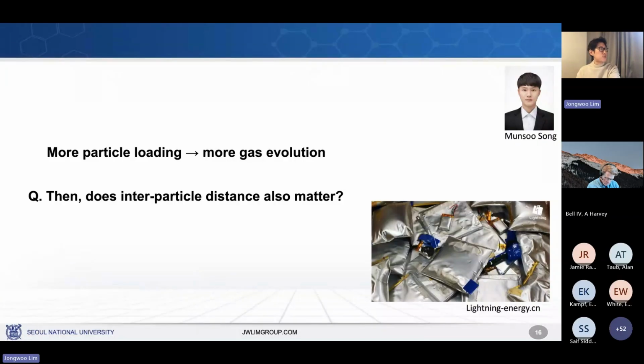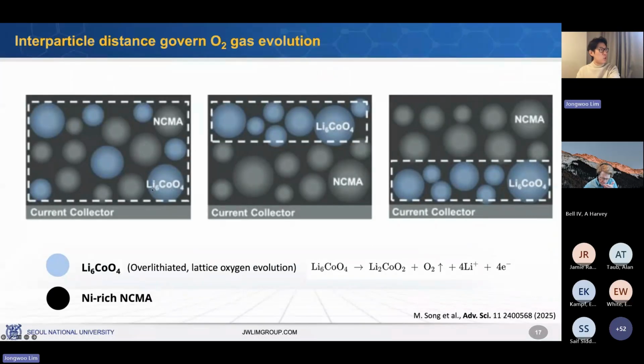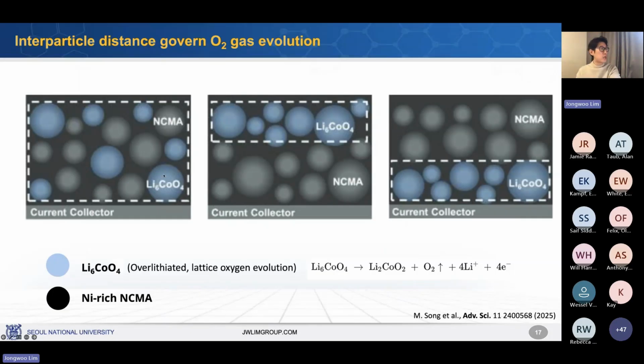So in a simple experiment, we include Li6CoO4, which is one of the state-of-the-art sacrificial cathodes. Basically, they produce a lot of lithium and also oxygen. The reason we put a lot of sacrificial or over-lithiated cathode here is that the anode's Coulombic efficiency is not 100%. They lose a lot of lithium. So they intentionally put a lot of lithium in the cathode particle, and they release the lithium to the anode, and then they just sacrifice themselves, and they're not active anymore in the second cycles. That's the main reason they use the sacrificial over-lithiated cathode particles in the cathode materials. But we are investigating it as an oxygen source because they also evolve oxygen at the same time.